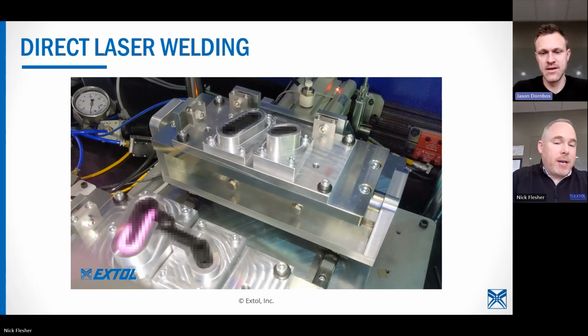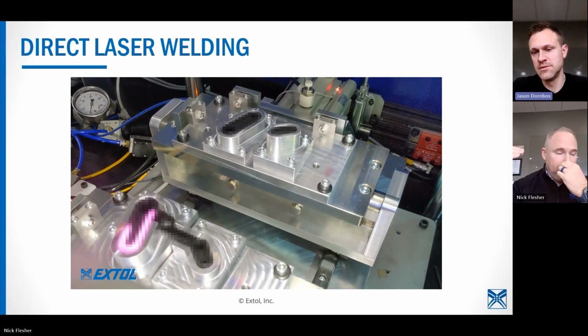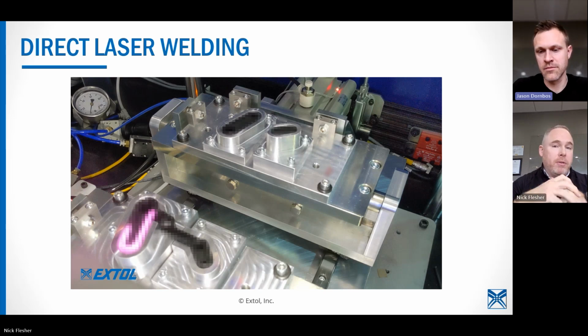So I want to pause. This material was a glass-filled nylon. And this particular customer was thinking ultrasonics. But if you're familiar with ultrasonics, you have to be very careful about what's called far-field welding, essentially having the energy source or the horn back up from the weld rib. We got pretty far down the project path, couldn't get good welded parts from multiple ultrasonic suppliers, and couldn't make it transmissive, and so we pivoted to direct laser welding for this.